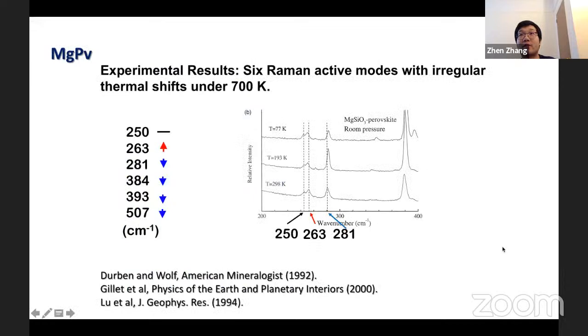From available experimental results, we know that Raman active modes of magnesium perovskite have some irregular thermal shifts under 700 Kelvin. As temperature increases, some modes' frequency remains unchanged, some modes' frequencies increase, and some modes' frequencies decrease. We will see whether the phonon quasiparticles can reproduce such irregular frequency shifts.